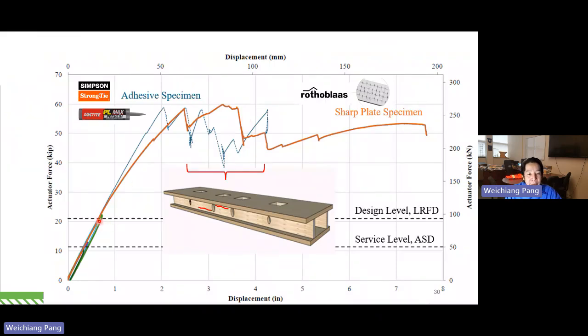So, yep, you can see that when we unloaded and reloaded it, it's not exactly following the initial path here. Part of it is due to a little bit of crushing at the support, so it settled down a little bit at the support here. And then when we reloaded it, it almost followed the initial path again. You're right, they are not completely linear elastic. There are a little bit of loops here. However, this is pretty minor. We don't see a big loop dropping here. There's not much residual displacement, but this is a good observation.